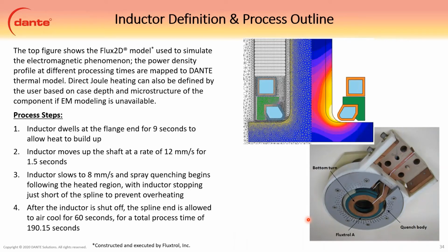In this particular model, the electromagnetics were modeled by Fluxtrol using Flux 2D. Then the power density, the Joule heating as a function of time and position, was mapped into the Dante thermal model to predict the temperature history. Once we have the temperature history, we can run the stress and get the displacements, residual stresses, and hardnesses. The Joule heating can also be defined by the user based on actual component case depth and microstructure. By doing that, we get a baseline of what the process does right now. We can then use that to modify and see how we can improve or optimize the process.